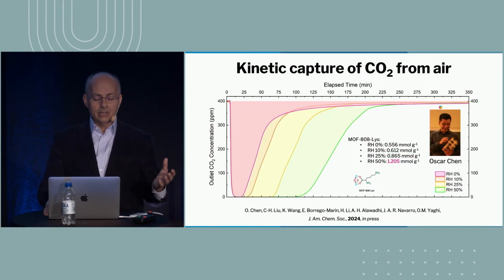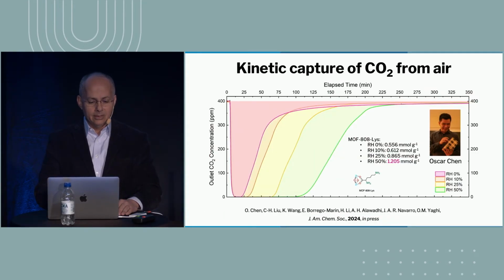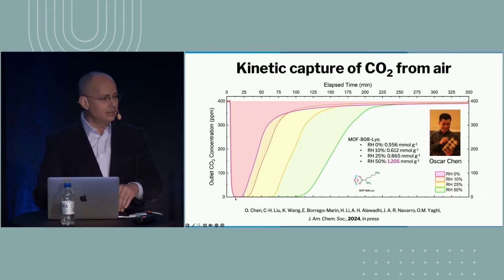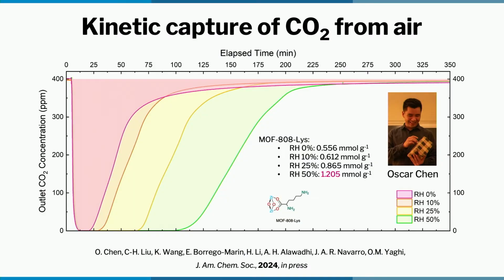Okay, so how does it work? How does it work in real air? So air is, as I said, 400 ppm CO2, and now I expose my MOF, the MOF I just showed you, to a wave of air containing 400 ppm of CO2, and this is the result. You see, immediately, CO2 is taken up by the material. It drops down to 0. So it takes CO2 out of the air.